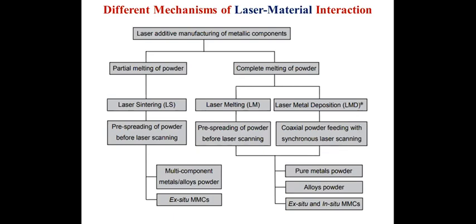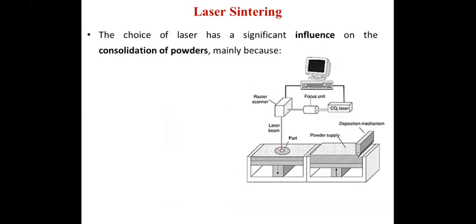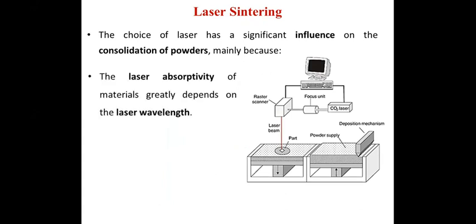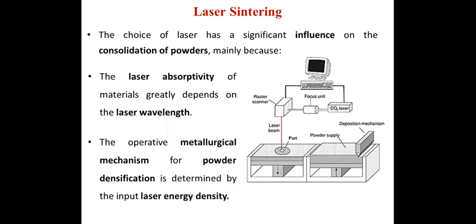In laser metal deposition, as we have seen in previous slides, coaxial powder feeding with synchronous laser scanning is the reason for the laser-material interaction of this mechanism. So as we know, in laser sintering the choice of laser has a significant influence on the consolidation of powders. The laser absorptivity of materials greatly depends on the laser wavelength: the lesser the wavelength, the more the absorptivity. The operative metallurgical mechanism for powder densification is determined by the input laser energy density.